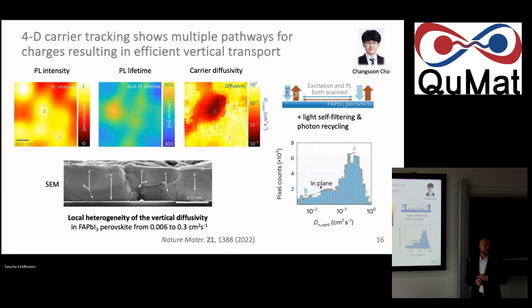And that's what is, again, heterogeneous. So more disorder. This time we look through the film, and you can probably rationalize this. I hope you see that a little bit here on this cross-sectional SEM image, scanning electron microscopy image. There are these buried grain boundaries even within the material, where you could totally imagine that the charge carrier has a harder time making its way straight through this if there's this grain boundary in the middle. So you can see the statistics here. It's really varied quite a bit, factor 50 or so, that you see higher or lower vertical diffusivity from pixel to pixel. So quite a heterogeneity here.